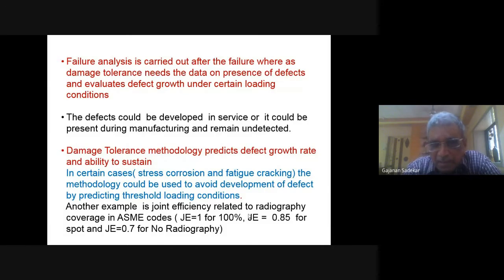For example, because of stress corrosion, some cracks can develop. Stress corrosion cracking can occur, or fatigue cracking can occur. In the beginning, you will not know. There may not be a defect available, and a defect will develop over a period of time. But that depends upon many things. For example, if you take stress corrosion cracking, it's a function of the stress, the medium, the temperature, and so many other parameters.